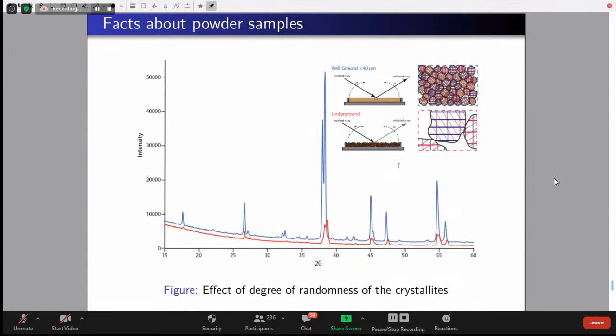Right. When we prepare these samples, how should we prepare them? For that, a good amount of explanation was there; here I will put it briefly. When we are making this powder, before going to the diffraction, we should always grind it and use some kind of sieve in order to get a very smooth powder. The smoothness should be like talcum powder, what we apply on our faces. There should not be any granular particles.